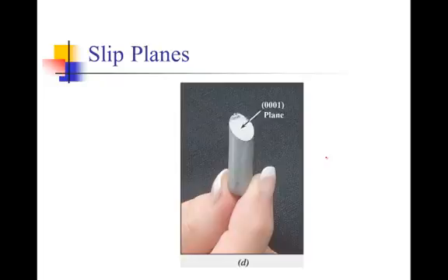And there's just an example of a piece of metal that has had some tension applied along the length of the rod, and the rod did not break with a horizontal fracture as you might expect with the force applied in that direction. Instead, it slips along a plane where the atoms are in a close packed arrangement with each other.